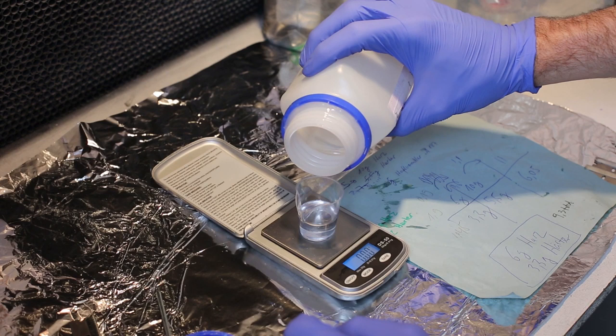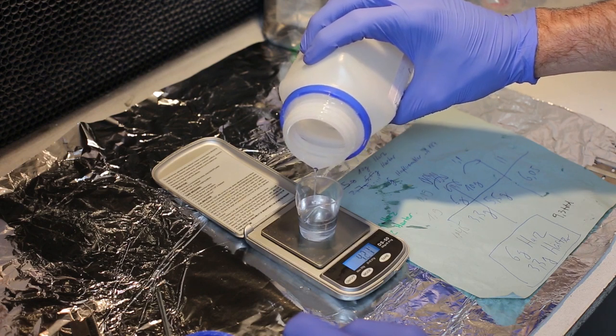UV glue can be used as well, but it has a tendency to yellow over time and generally makes for not as strong of a bond as epoxy glue does. The epoxy glue consists of part A and B. The instructions for my brand of glue are 12 grams of resin and 6.6 grams of hardener. Today I'm using a budget glue, but if you have a hologram that you want to seal forever, I recommend the product HXTAL-NYL-1. This is a special epoxy glue which is mainly used in museums for archival purposes.